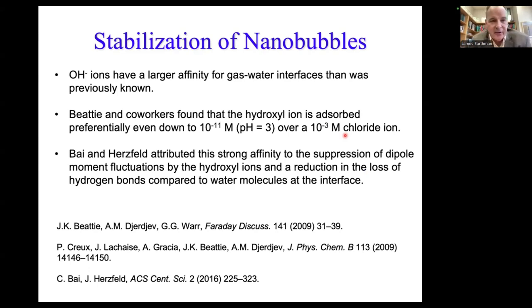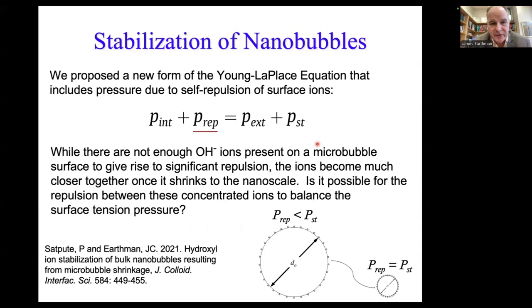All right, so we started looking at how OH ions could be doing this. And it turns out, not long before this, there were some publications which showed that OH ions actually have a huge affinity to gas-water interfaces. They will knock other ions like chlorine ions off the surface, off the gas-water interface, to get there. And this was being reported. Bai and Herzfeld, as you can see there in the third bullet, attributed this strong affinity to suppression of dipole moment fluctuations by the ions and a reduction of the loss of hydrogen bonds compared to water molecules at the interface. So there was a lot of literature and evidence to support the idea that OH ions have a much lower energy at a gas-water interface, and they want to stay there. So we introduced another term to the Young-Laplace equation.